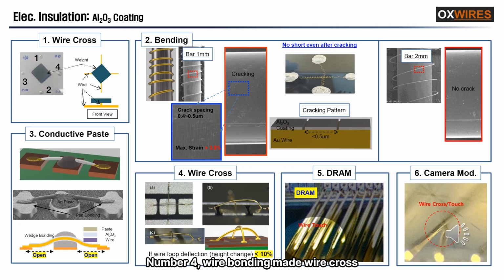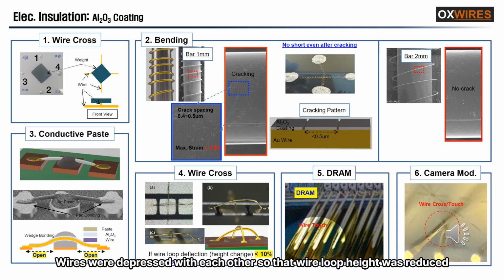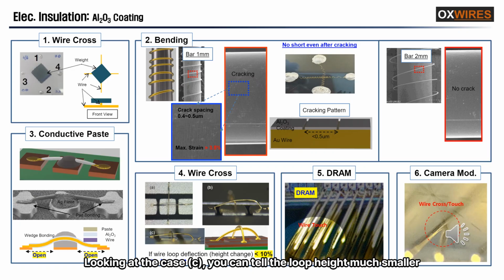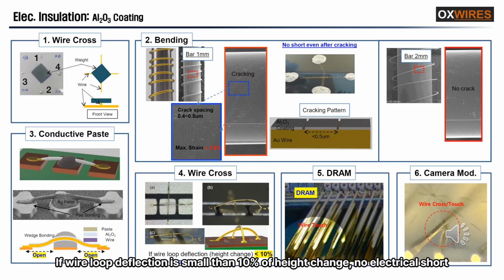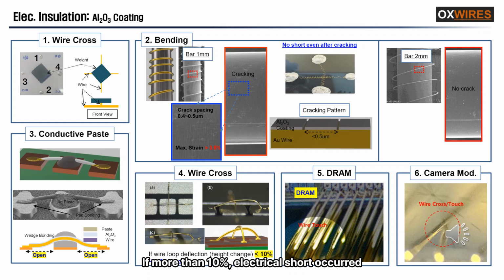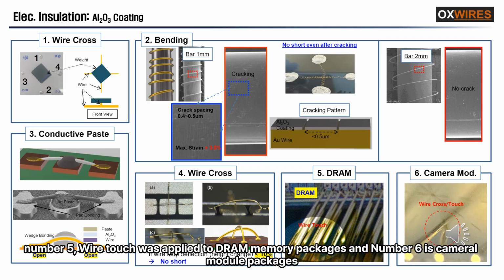Number 4. Wire bonding made wire cross. Wires were depressed against each other so that wire loop height was reduced. Looking at case C, you can tell the loop height is much smaller. If wire loop deflection is smaller than 10% of height change, no electrical short. If more than 10%, electrical short occurred. Number 5. Wire touch was applied to DRAM memory packages, and number 6 is camera module packages.